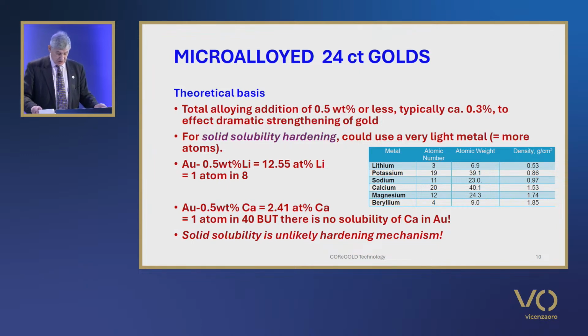Such small additions are approaching those values typically used to control grain size by grain refiners, such as cobalt or iridium in karat golds. As gold is a low stacking fault metal, and stacking faults are a type of crystal lattice defect, control of grain size alone or in combination with cold work will not yield significant hardening in pure gold. So such small additions cannot work through grain size control only.